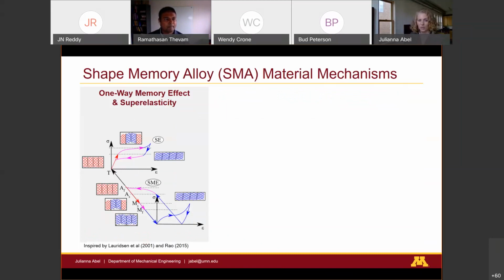Many of you are probably familiar with shape memory alloys. The most common effect is the superelastic effect, and that's what's been implemented in countless implantable medical devices. Where you are above a transition temperature and you exhibit this constant stress plateau. So you are linear elastic for a portion of time under loading, and then you undergo this constant stress plateau, and then you can recover all that deformation upon unloading. These materials can exhibit up to 8% recoverable strain, and this is all at high temperature, above the austenite finish temperature.